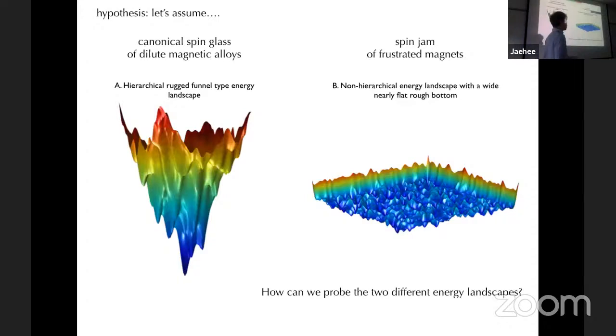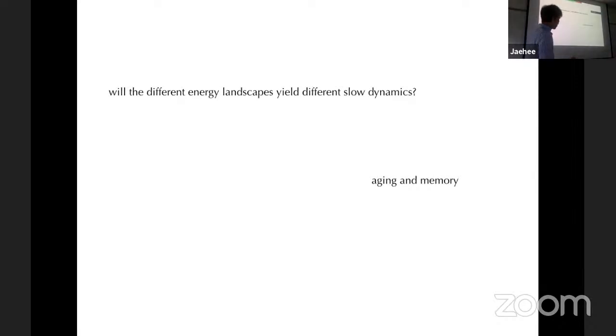So I will say that there are two different kinds of glassy magnetic state. One is a spin glass and one is spin jam. Without worrying about microscopic origin, let's assume that the canonical spin glass has this rounded funnel-type energy landscape. On the other hand, the glassy state of a fluctuating magnet that we call spin jam has this kind of non-hierarchical energy landscape. Let's just assume this and see whether the hypothesis works for explaining experimental data. So how can you prove these two different energy landscapes? Experimentally, we can do that by measuring the so-called aging and memory effect.